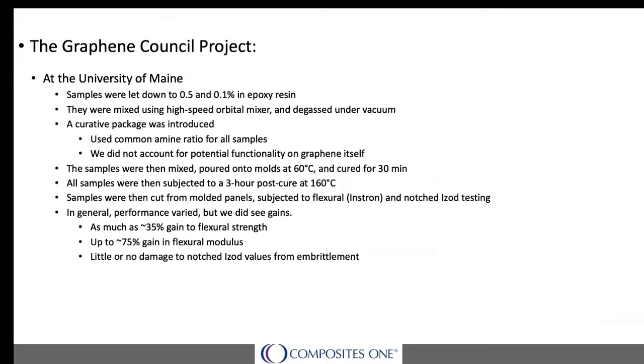As Paul mentioned earlier, we had 17 sample materials shipped to the University of Maine for testing. These samples were anonymized, and no one, including myself, knew whose material we were testing, giving an unbiased, objective testing protocol. We took the 17 master batch samples that Vibrance did and blended them down to the 0.1% and 0.5% loading of graphene by weight into the bisphenol F epoxy. We poured the samples into a mold and cured at 140 degrees Fahrenheit for 30 minutes, followed by a 3-hour post-cure at 320 degrees Fahrenheit. The samples were then cut from the molded panels and tested for both flexural properties and impact toughness.